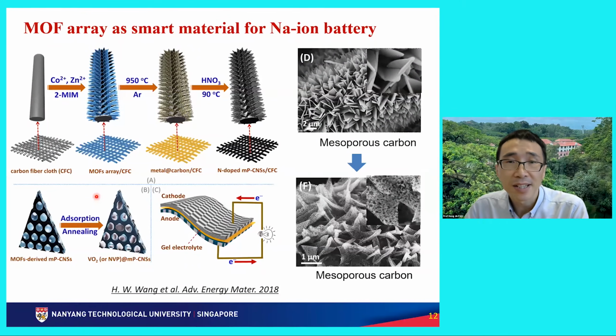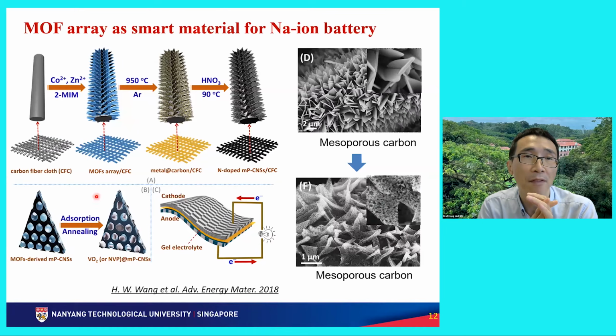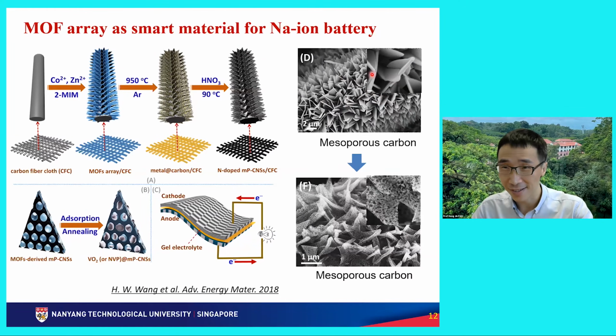In a similar work, we use a very popular material called MOF, metal organic framework. Metal organic framework is also kind of a good material that has a very wide range of applications. People use it for energy storage and conversion, like electrocatalysis and energy storage. So in this work, we grow this MOF array structure on a carbon cloth. Cloth is like your clothes, but it's made of carbon. This kind of cloth is made of a lot of carbon fibers. The fiber surface is densely covered with grass-like MOF structures. Then after some treatment, we remove the metal ions, anneal them in argon, and convert these flakes into porous carbon flakes.